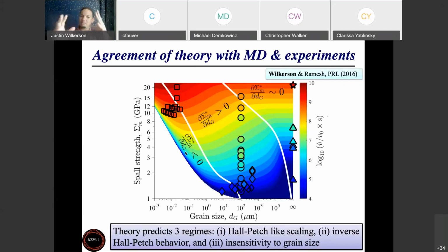Okay. And so this is a competition that's going on where as I decrease the grain size of the material, I make it harder to grow voids because the material is just stronger due to Hall-Petch strengthening. But because grain boundaries are void nucleation sites, I have more places to nucleate voids. And so there's a competition there in terms of whether decreasing grain size will enhance or degrade spall strength.